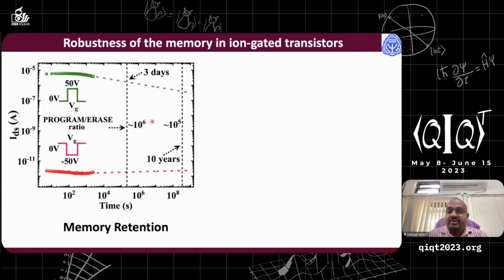And now coming to the very important observation that we have seen, when you give a pulse voltage of say 50 volt to these devices, and once you apply a gate voltage of say 50 volt, and you change the conductance of the system, you measure over time how long that conductance stays unaltered. So we wait for say 10 to the power 3 seconds, and you see there is a small decrease in the current.